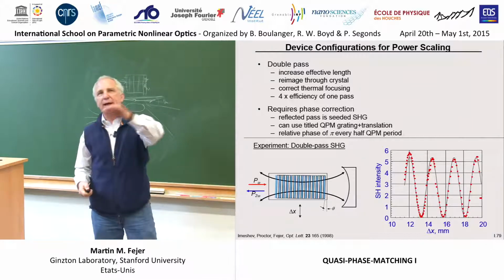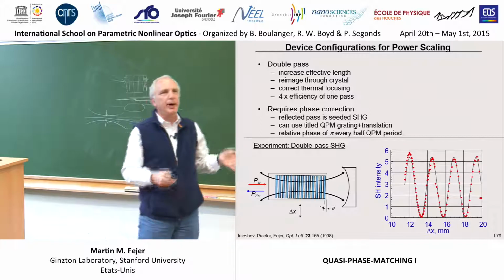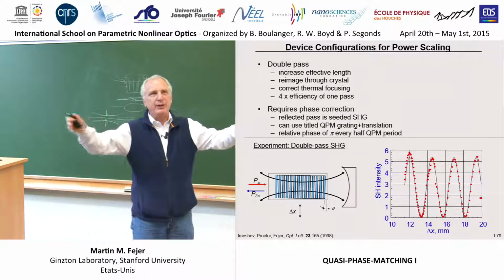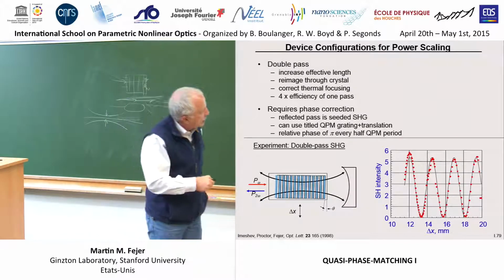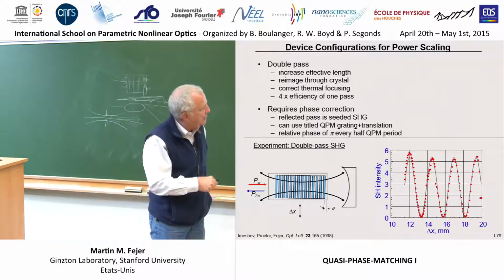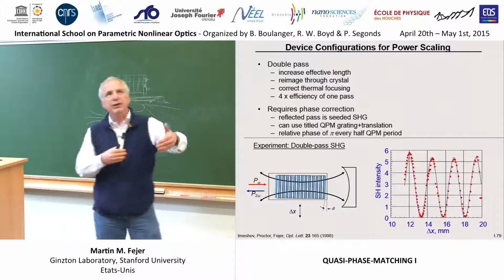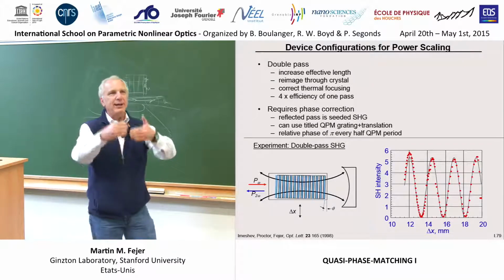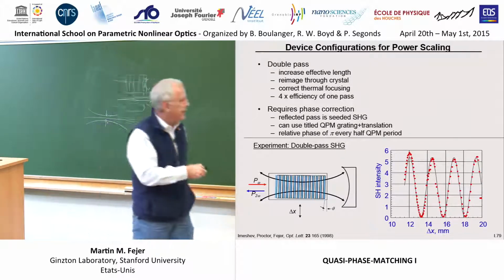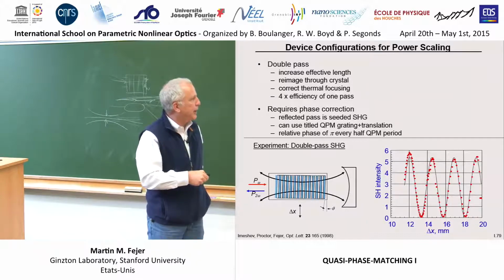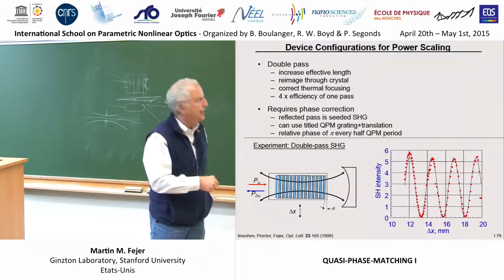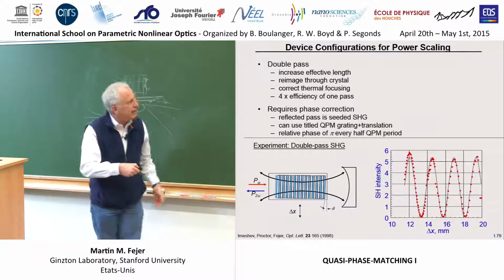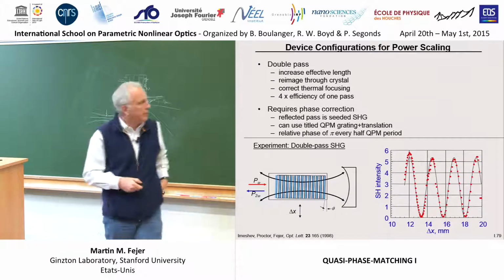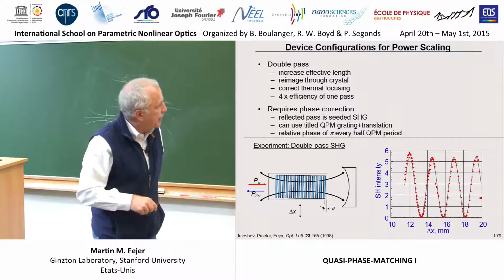Since you get a pi phase shift between the fundamental and the harmonic for every coherence length in a quasi-phase match structure, as you translate this thing through the beam and you have different widths of this last stripe, you can continuously vary the relative phase between the fundamental and the harmonic that are exiting the crystal, and you can pick the one such that a round trip puts you back at the proper phase as you go through the rest of this crystal. And this is a plot of such an experiment.